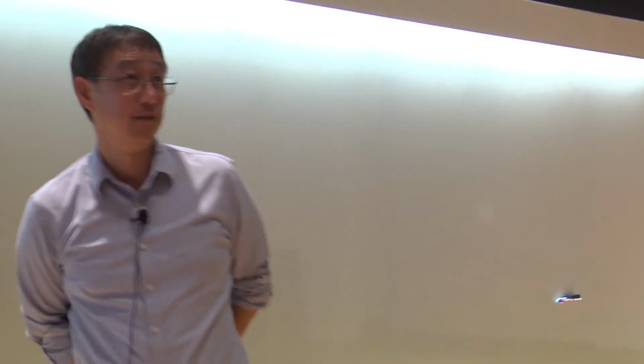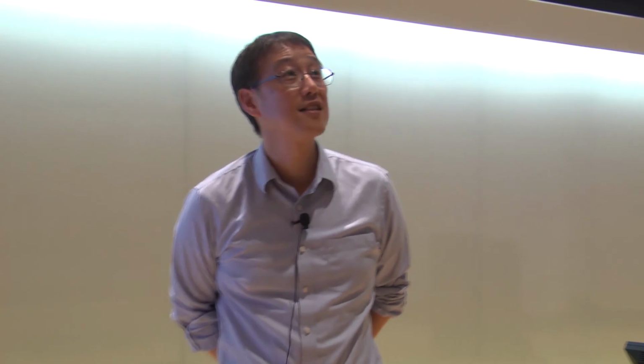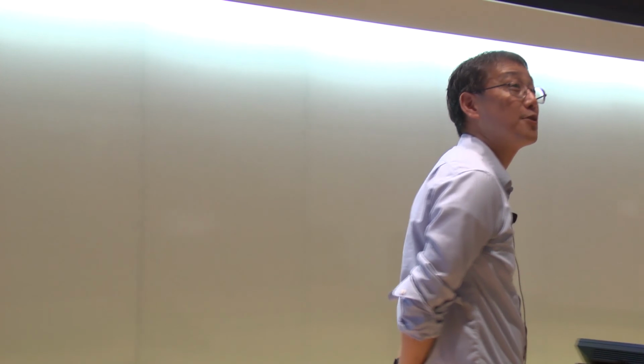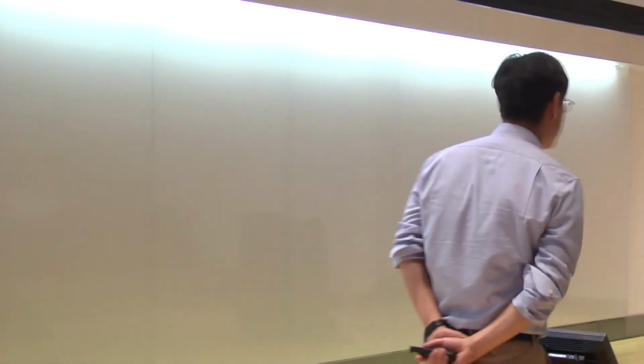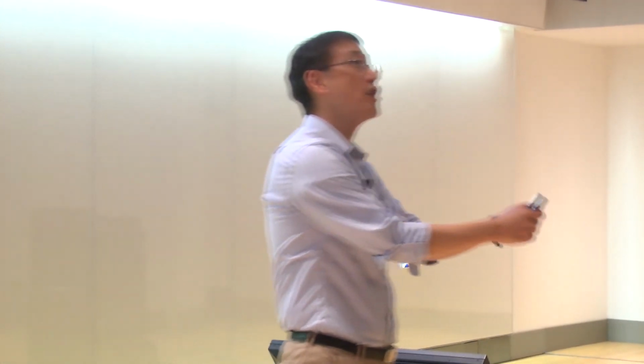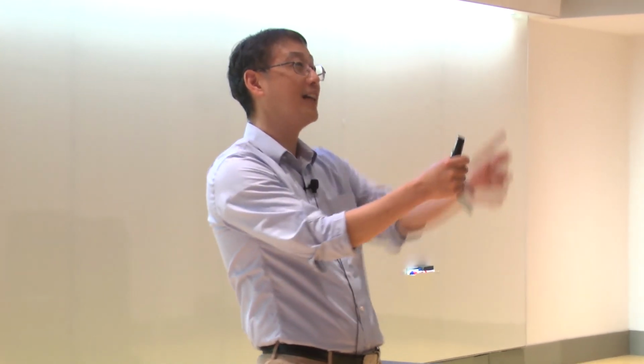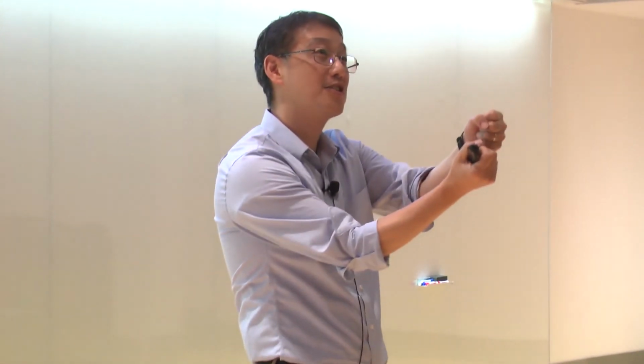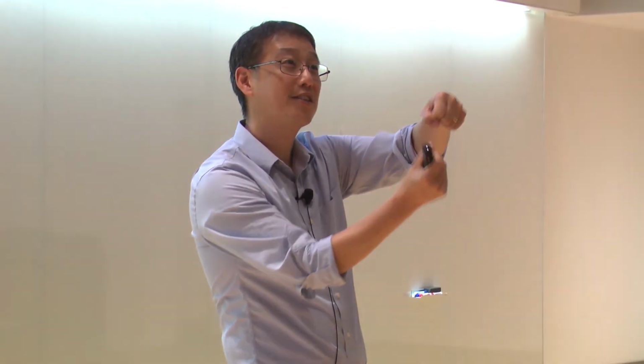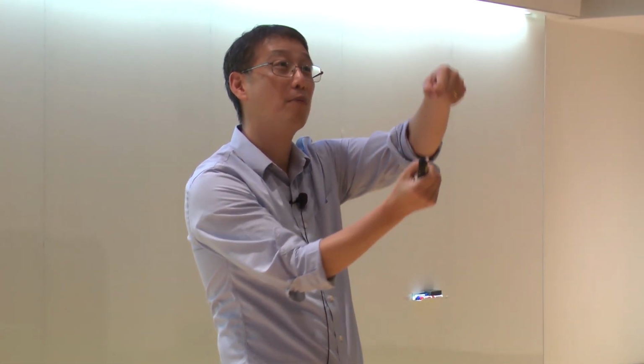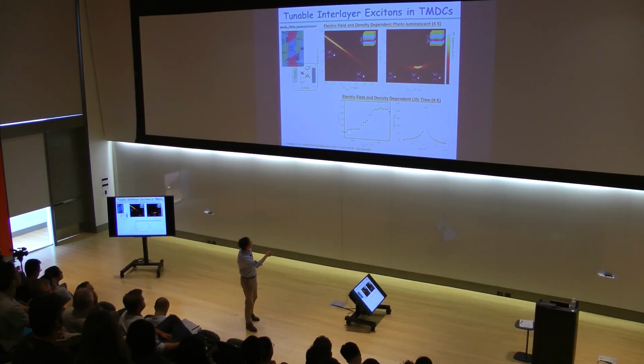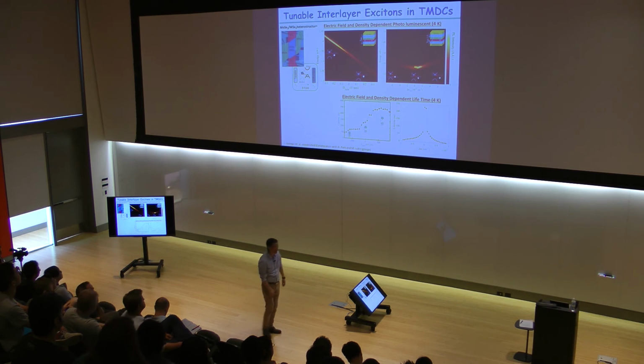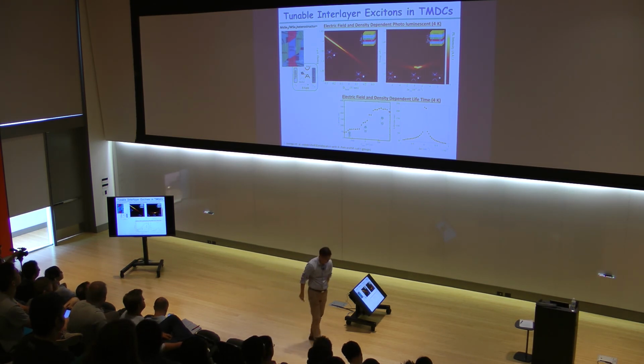And just looking at the magnitude of the linear shift, we know that this is a completely interlayer exciton we just created. Now, I told you the interlayer exciton can be long-lived. Indeed, if you just look at it, the exciton lifetime is reasonably long. It's something like 200 nanoseconds to half a microsecond. More importantly, as you change the gate voltage, as you apply the electric field along the exciton direction, such that you start to pull these excitons away, you start to get the electron and hole wave functions overlapping less and less, and you expect the lifetime becomes longer and longer. And that's precisely what you see. As you apply the electric field, the lifetime becomes longer because you pull these excitons out, right?